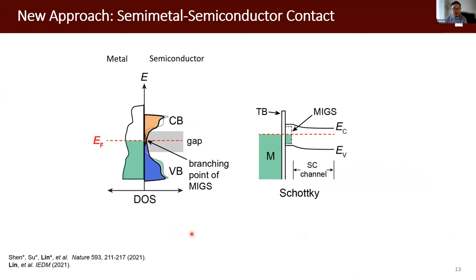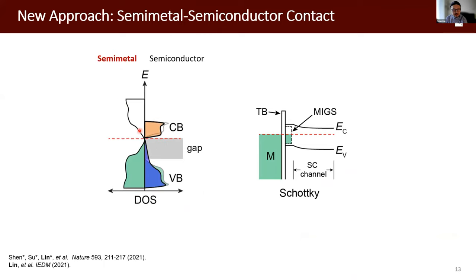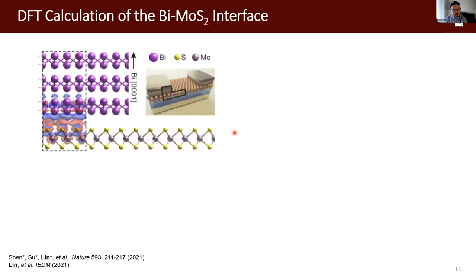We came up with a new contacting strategy. If we replace the metal with a semi-metal around the charge neutrality point, the density of states is close to zero or very low. As a result, the metal-induced gap states around this energy level would also be low. If this point aligns with the band edge of the semiconductor, it's very likely we can mitigate the metal-induced gap states and make the Fermi level aligned at the band edge of the semiconductor.